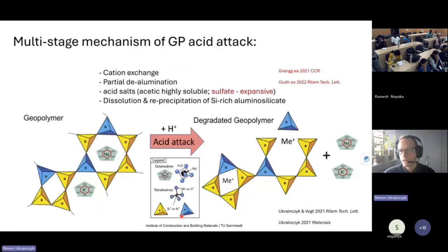So this is the mechanism for geopolymer acid attack, which we have published in also many papers. And basically you can see that the proton is attacking first, it's an ion exchange of proton with potassium or sodium. So we have here the protons, so then those are more leachable. And then later this proton also attacks the aluminate, so we have the dealumination reactions.